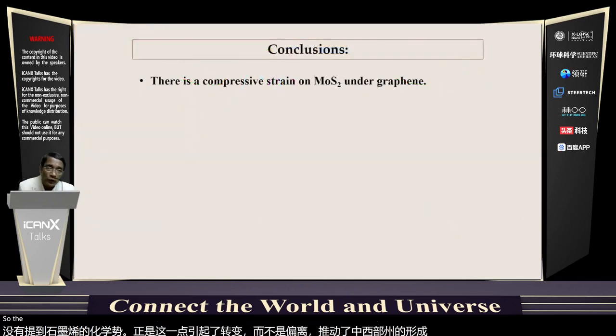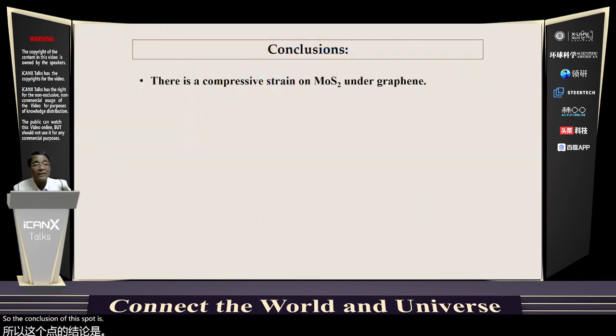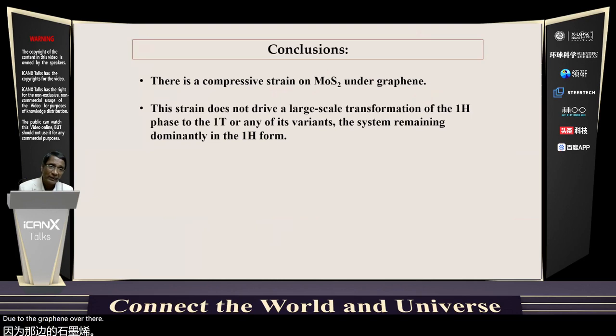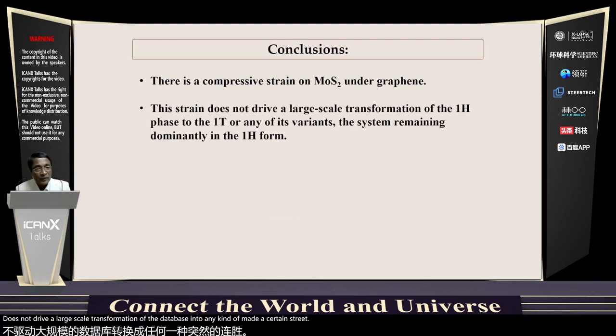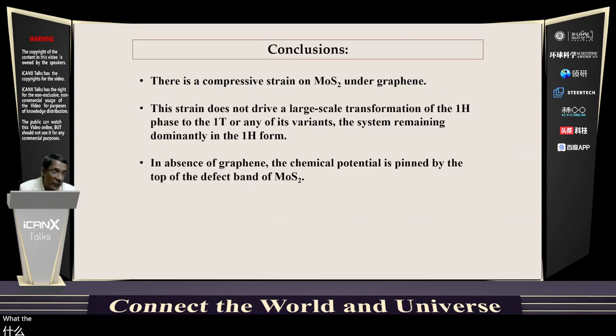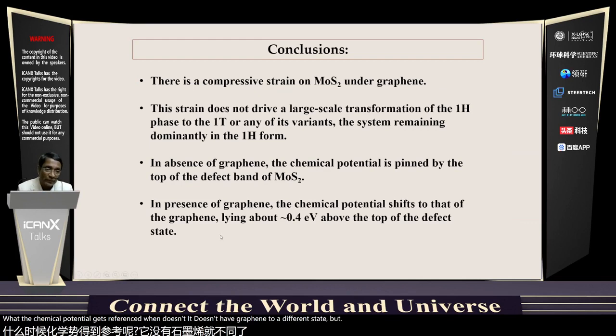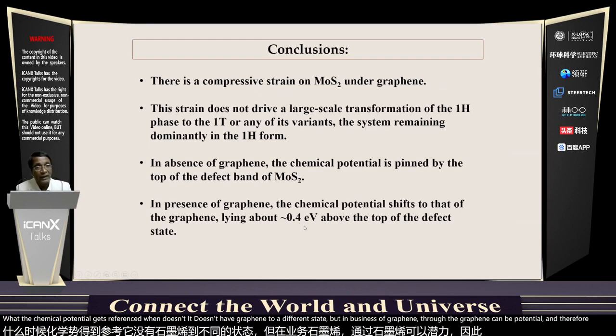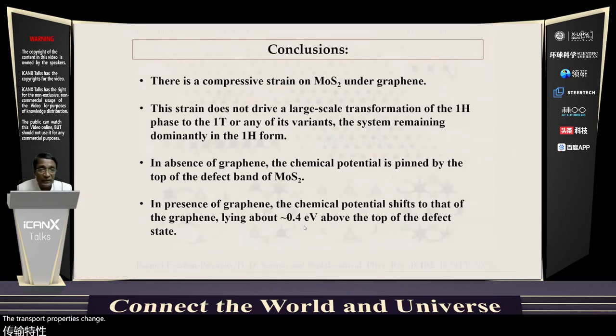So the conclusion of this part is that though it was believed that the compressive strain, which does exist due to the graphene overlay, drives a large-scale transformation of the H phase into some kind of metastable state, it does not. Instead, the chemical potential gets referenced to a defect state when it doesn't have graphene, but in the presence of graphene to the graphene chemical potential, and therefore the transport properties change drastically.